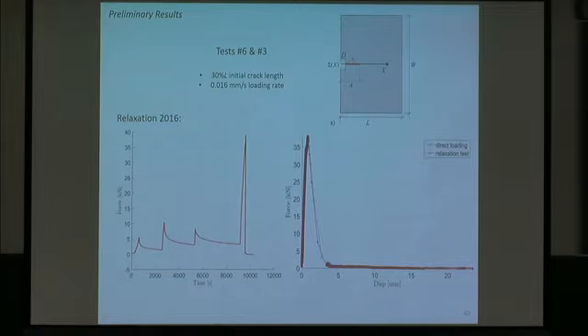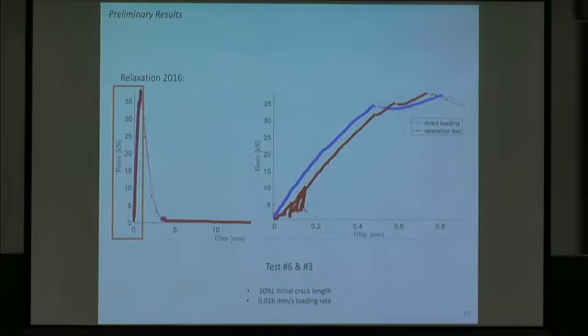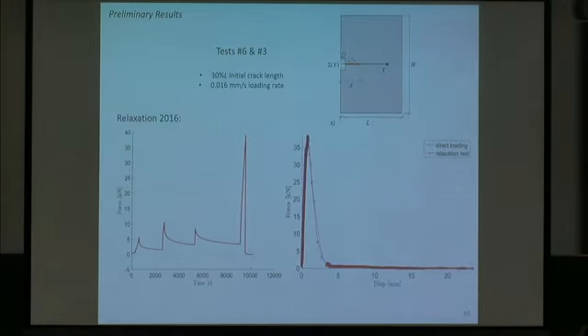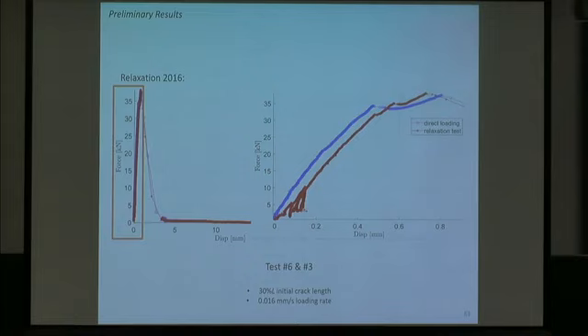So this is a relaxation test we did in 2016, and it was done with a loading rate of 16 micrometers per second. And in 2017, early this year, we repeated this test. Oh, sorry, I should say, let's look further at this image. We just zoom in to see how this relaxation looks. You see that we almost have the same peak, and the trend also looks almost identical, except that for this red curve we have some back and forth of these relaxation cycles.